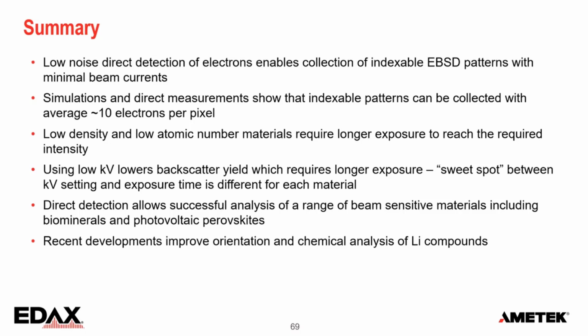I find that in general, I get most of my results at 8 kV to 12 kV and beam currents between 50 and 200 picoamp. In that range, I could get EBSD mapping data on, for example, all the perovskite samples that I've shown. That allows you to have a nice successful analysis of beam sensitive materials, including biominerals that are sensitive with organic material and these perovskites. And then some recent developments to improve the orientation and chemical analysis of lithium compounds as well.